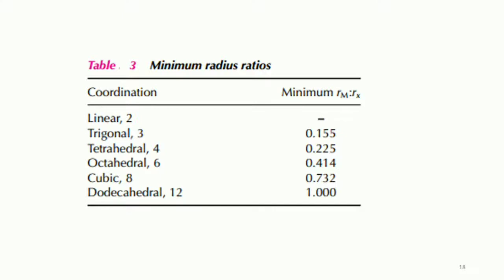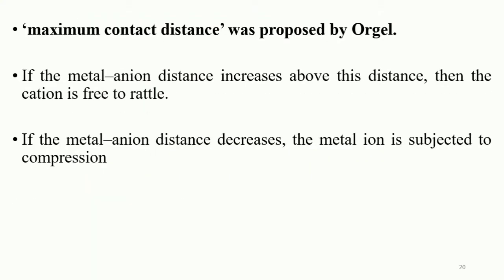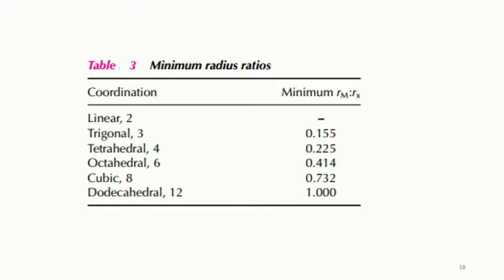So, for example, if we talk about rubidium iodide, the radius ratio is equal to 0.69, or sometimes we can write 0.8 according to the tables. Based on this radius ratio, one would predict 6 coordination, as in rock salt, which is observed, but the other predicts 8 coordination like cesium chloride. On the other hand, lithium iodide has a radius ratio equal to 0.28. According to some tables, the values predict tetrahedral coordination and according to others octahedral.